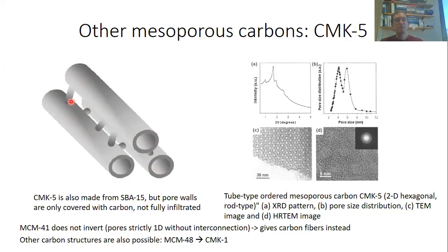So you still have these cylindrical mesopores that are straight in your carbon structure, but you also have pore space in between these cylindrical mesopores, because the cylindrical mesopores are interconnected by little rods due to the presence of the microporosity in the SBA-15 template. Okay, so you see here how you can actually characterize a material like this.